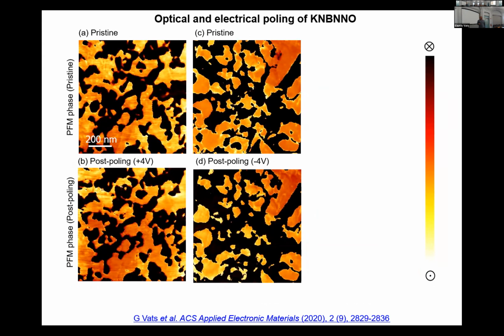I poled the whole area with +4 volts, and I acquired the image of the same area again. Now, if you look at any of these features, for example this one, you can see that the bright yellowish domains are expanding. I did the same thing with the negative bias. And here you can see that these bright yellowish domains are actually contracting. And in some places, they are broken into two. For example, if you focus on this feature, it's broken into two domains.